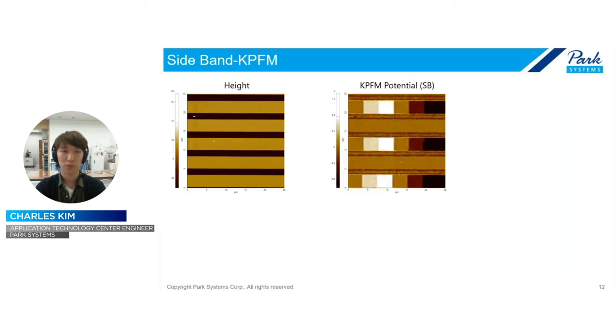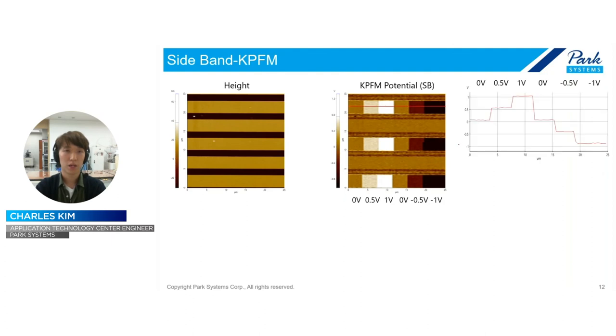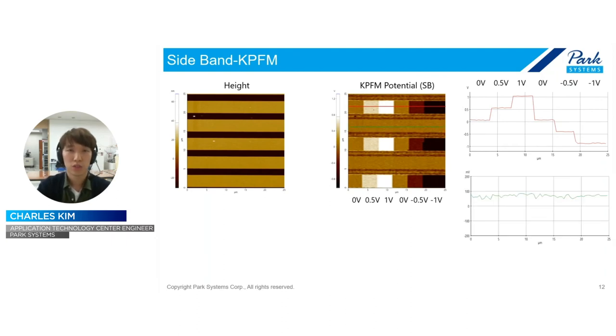So let's see the rear image. I already measured the same images by using the sideband KPFM. So when you see the sample bias applied to the electrode here in the red line, you can see 0 is almost 0, 0.5 is 0.5, 1, 0, minus 0.5. But there is some small gap here, and this gap is from the tip's potential. So to know the exact work function of the sample, we need to do the calibration to compensate this kind of small offset.